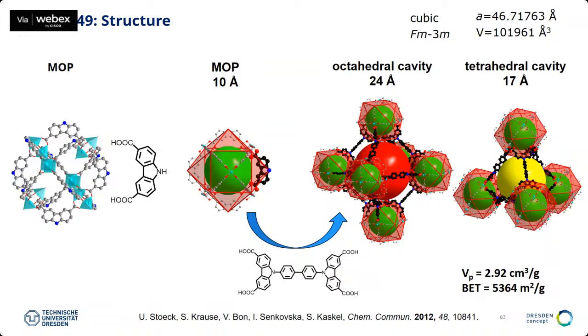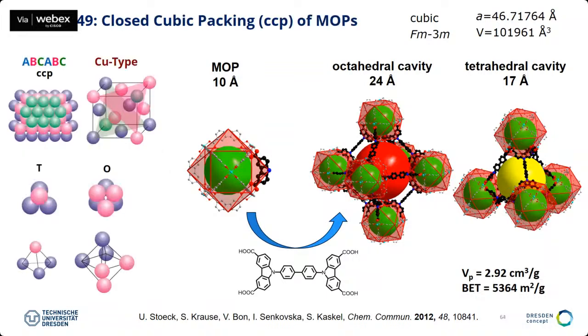So you have the MOP, which is porous, but then you also have huge pores, which are mesoporous, 2.4 nanometer and 1.7 nanometer. And it looks a bit complicated, but this structure is very familiar to all chemists and material scientists because it resembles the copper metal structure. I think you're all familiar with the CCP metal structure of copper. It's a cubic close packing. We also call it face-centered cubic, a very simple structure. Essentially, here you see some of the models, the ABC copper type structure.